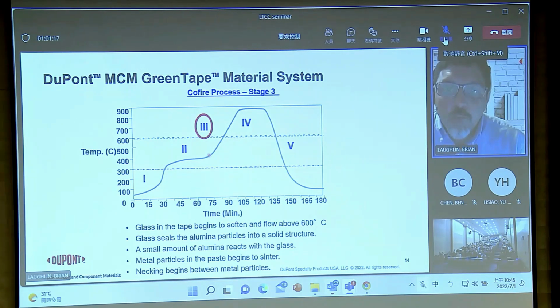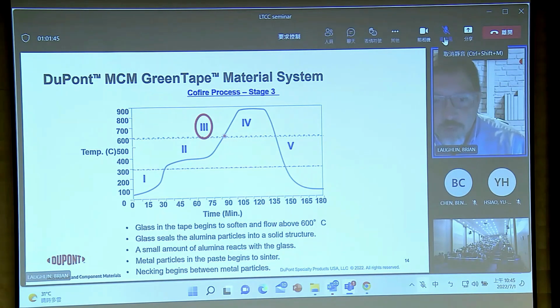And so depending on the system, 951 has a pretty wide process window and a lot of latitude to change the heating rate in this ramp up. But in here is when you hit the Tg of the glasses and sintering starts occurring, and you're going to start creating the microstructure that's the high quality dielectric that you want in the end. 9K7 is a very high performance material, but has much more restriction on the heating rate in this final ramp.